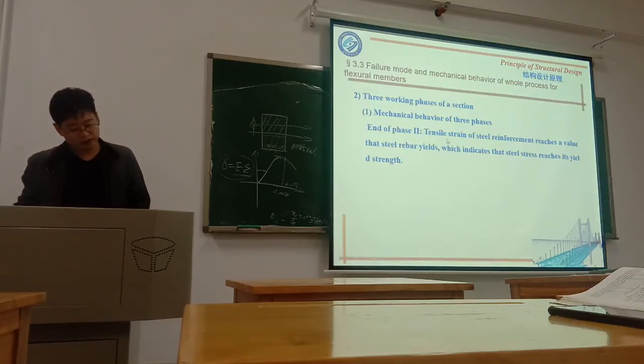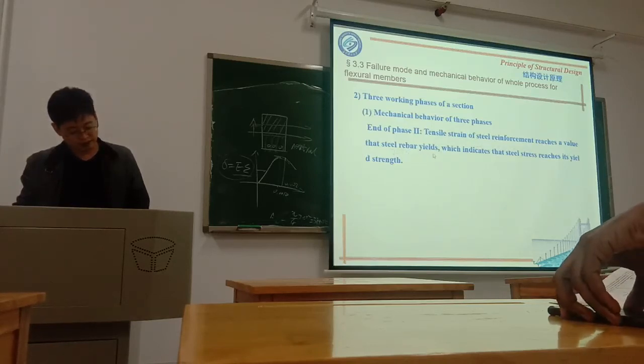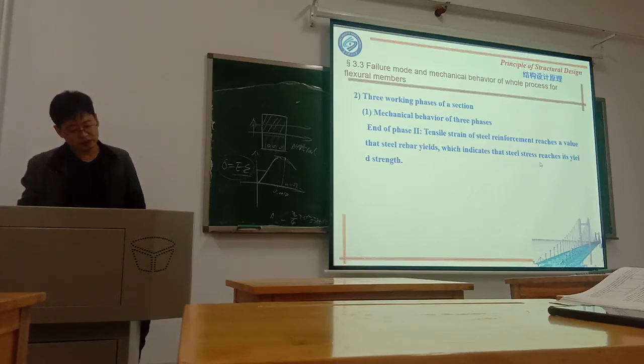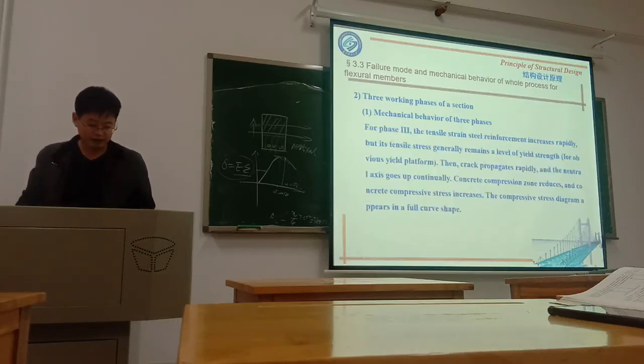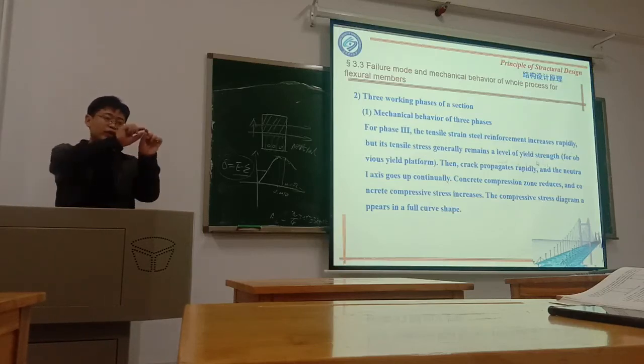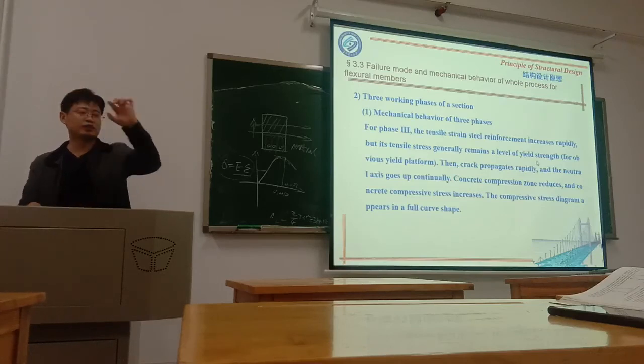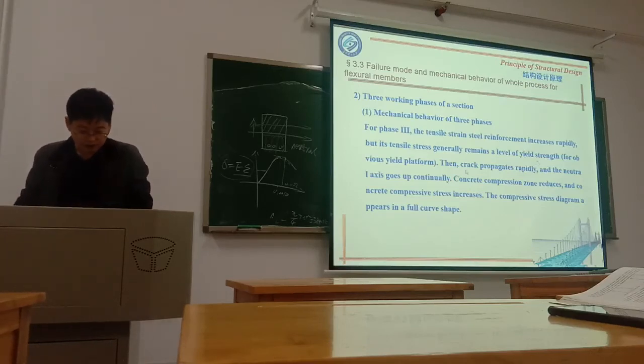At the end of phase 2, the tensile strain of the steel reinforcement reaches the value at which the steel bar yields, which indicates that the steel stress reaches yield strength. And for phase 3, the tensile strain of the steel reinforcement increases rapidly, but the tensile stress generally remains at the level of yield stress. So the strain increases greatly, but the stress remains nearly the same level. Then the cracks propagate quickly, and the neutral axis goes up continuously. The concrete compression zone is reduced, and the concrete compression stress increases. The compression stress diagram appears in a full curve shape.